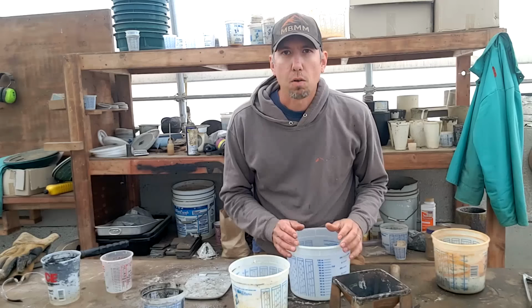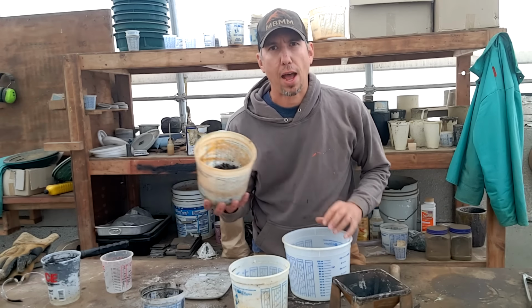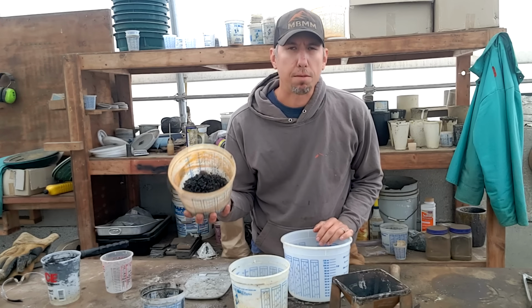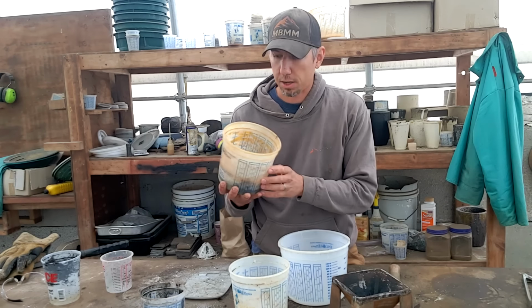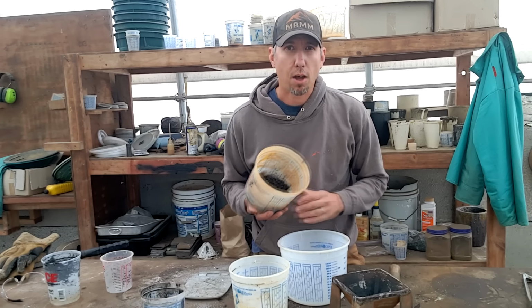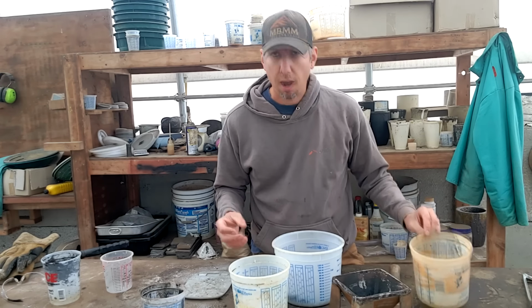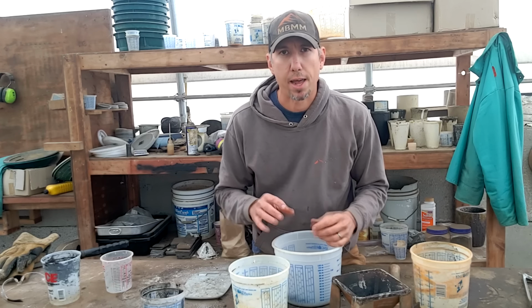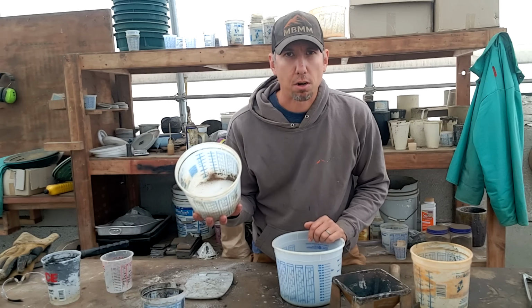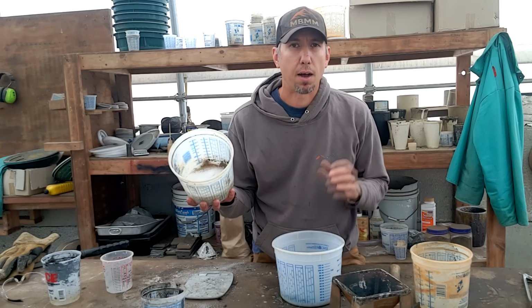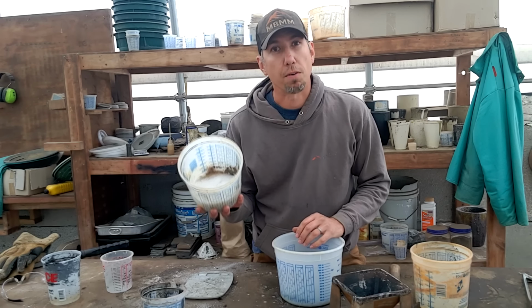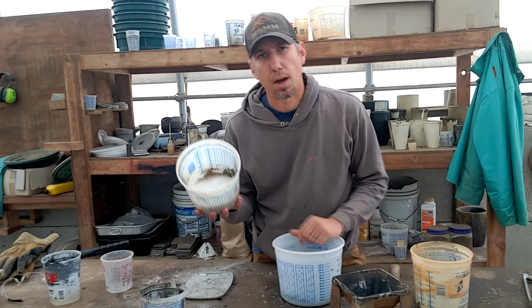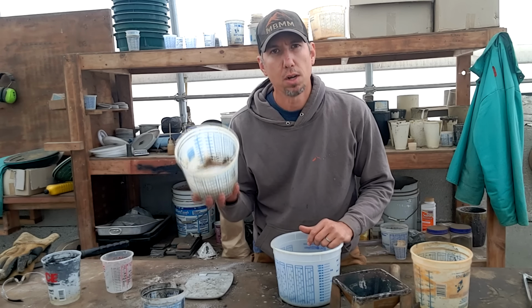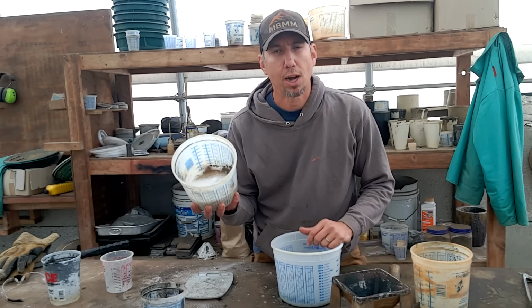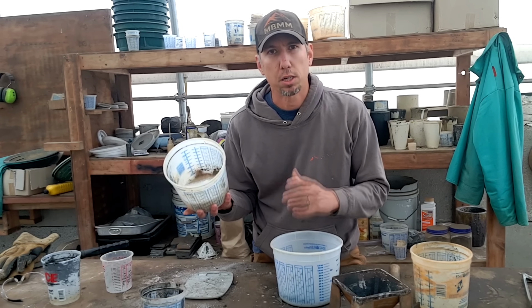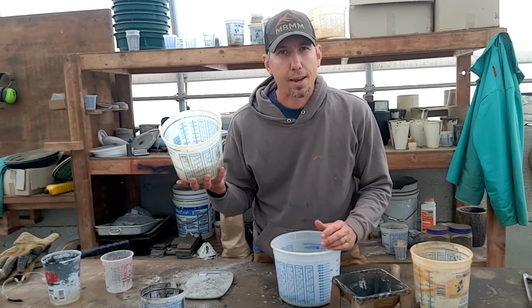We'll see what happens. Well, my chemistry is a little bit rusty, but we've got about 1,000 grams of lead here, and each mole of lead weighs roughly 200 grams. So we have a total of about 5 moles of lead here. To oxidize all that away, we need about 5 moles of oxygen to combine with the lead. So I have 500 grams of potassium nitrate here, which is about 100 grams per mole. Each mole gives off 1 oxygen, which will combine with our lead to form PbO. So for our 500 grams of potassium nitrate and our 1,000 grams of lead, that should equal 1 oxygen atom for every lead atom, and it should oxidize all the lead away.